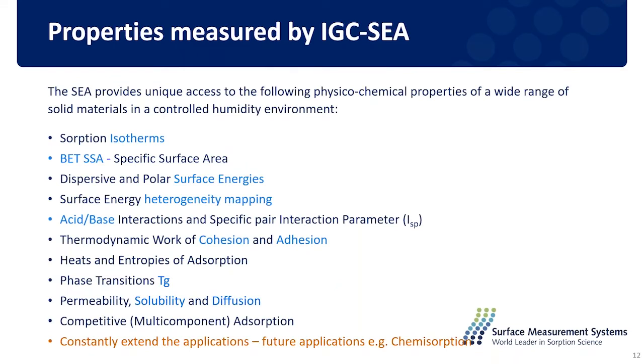So the IGC technique is very versatile for different kinds of thermodynamic properties. We can measure a list of different properties from the injection of the organic vapor. If we do a single organic vapor injection, then we can get a full isotherm of the material. Then from the isotherm, if it is a type 2 or type 4 isotherm, we can determine the BET surface area of the material.